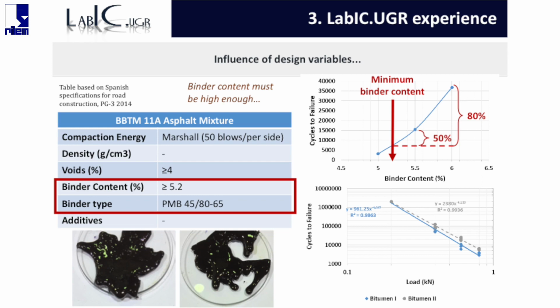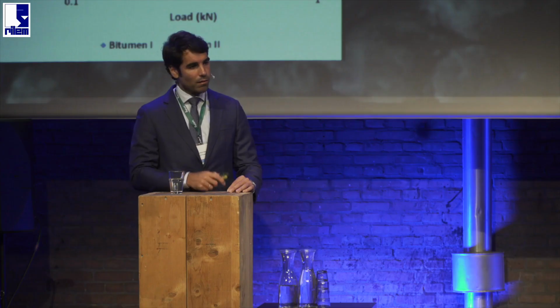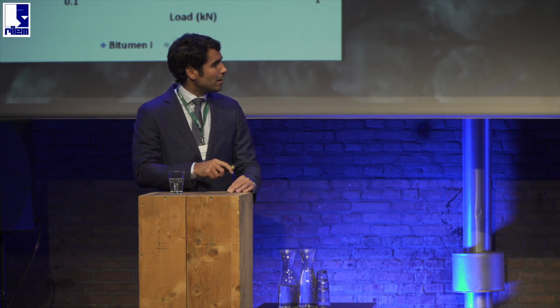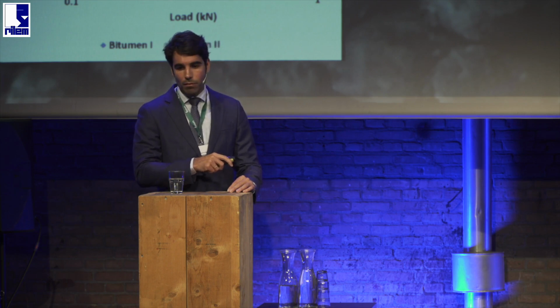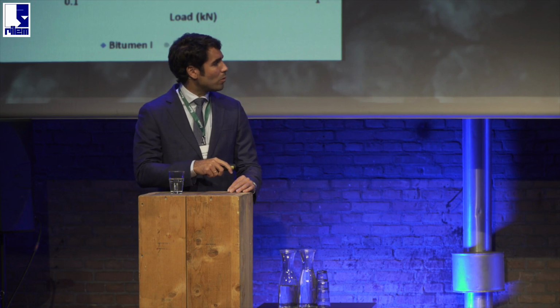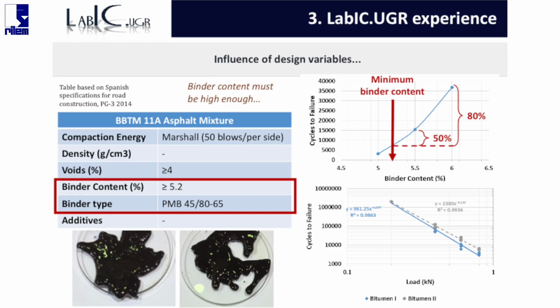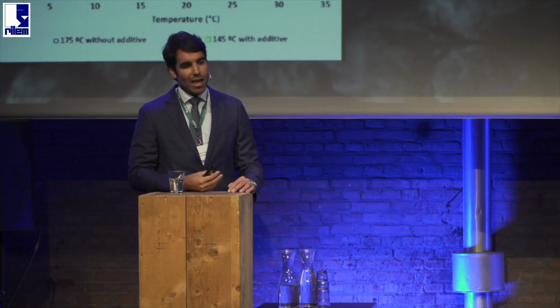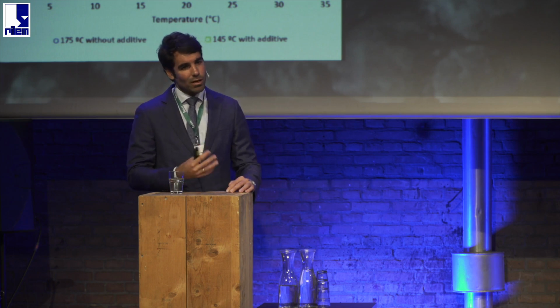In addition, many binders can accomplish those standards of polymer modified binder. But if you take two different types of this binder and you pick a more elastic one, you can notice a considerable increment in the fatigue life of this material, especially when the loads are higher. And in the end, additives are usually not advised when you are designing asphalt material because they increase the cost and all that.